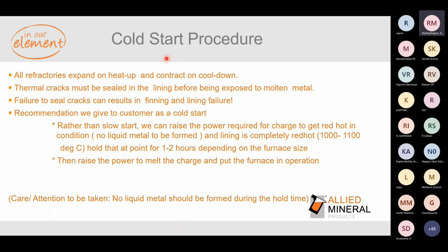It can be fast. You can raise it as fast as possible, but make sure the charge is in red hot condition. So the lining is in red hot condition, but care should be given that the metal should not melt. The charge and the lining should be in red hot condition. At that stage, hold for 1 to 2 hours, depending upon the size of the furnace. During this hold, refractory expands and gets sealed actually. So this is the important stage, because you need to allow the refractory to expand.